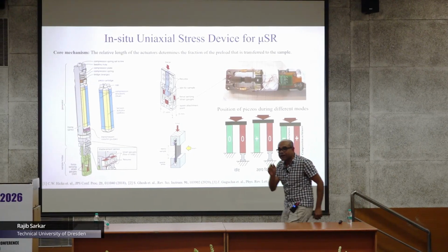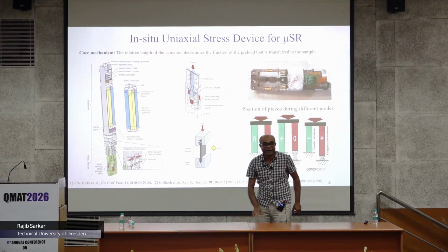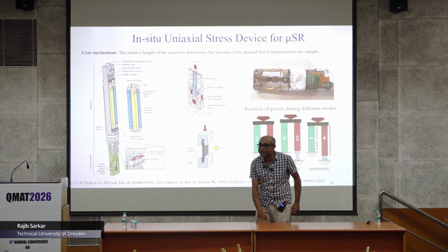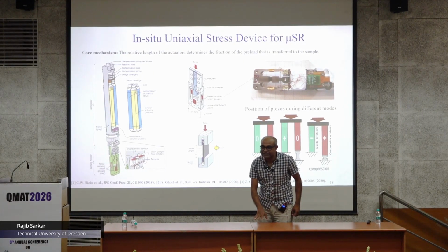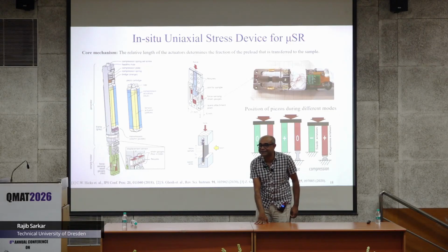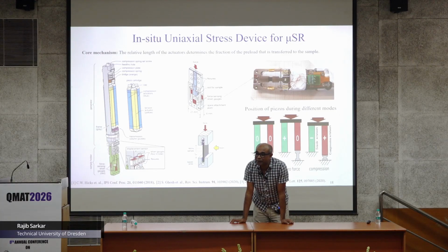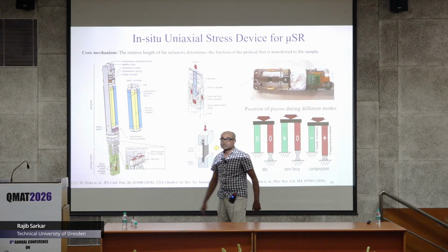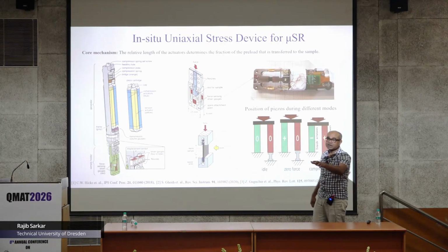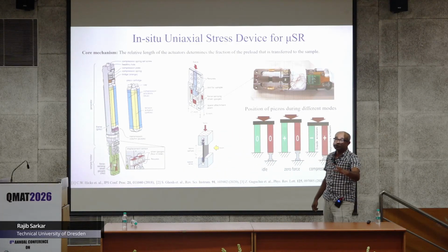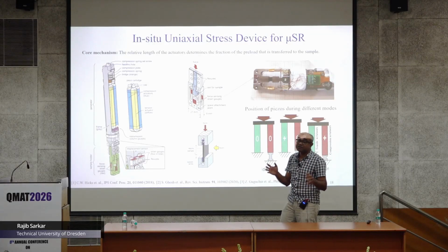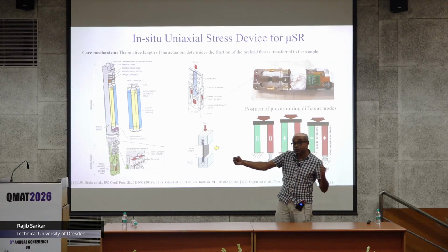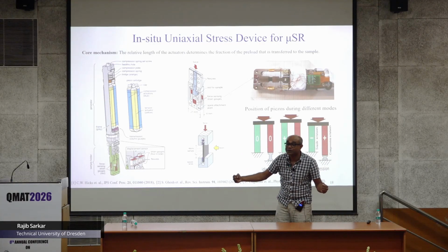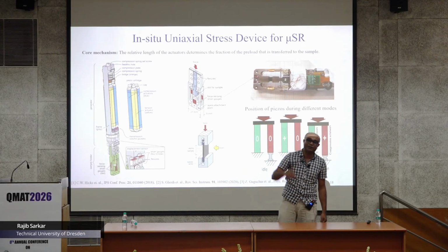Of course, if you have a tiny sample, like for thermal conductivity, AC susceptibility or magnetization, then you need only a 1 millimeter sample. Then it's easy, and you need very small piezos. Only 20 volts or 30 volts, or maximum 50 volts, is enough. But here you need 250 to 300 volts, or if you use 2 stacks, you need 600 volts, which is very demanding. Therefore, a diamond cell will not work.